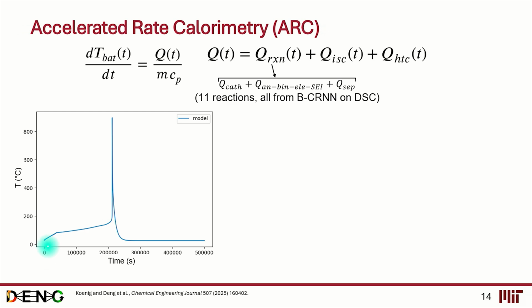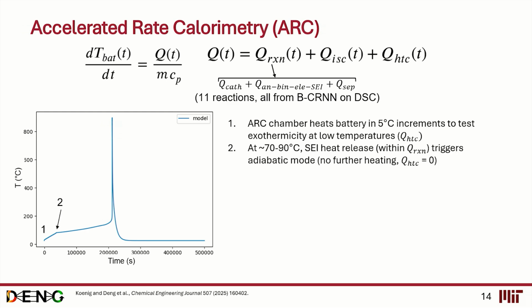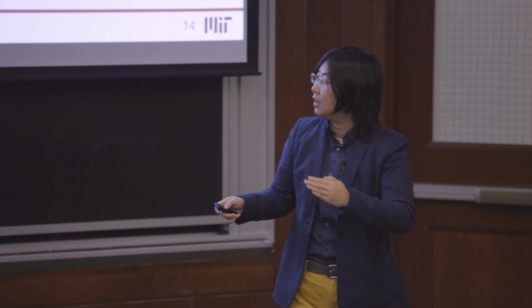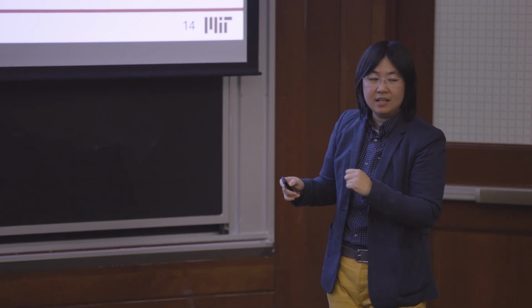You cannot see it, but this figure is keeping track of the time the battery spent in the reaction chamber, and the temperature of the cell. You can control the heating rate and the environment inside the chamber. The battery is heated at a relatively slow heating rate. After you heat it, you wait a few minutes to see if the temperature changes. If the temperature doesn't change above your setting temperature, you can continue the heating process. And you can see that from point 1 to 2, after you stop heating, the battery will start self-heating. And this is the trigger of heat release processes.